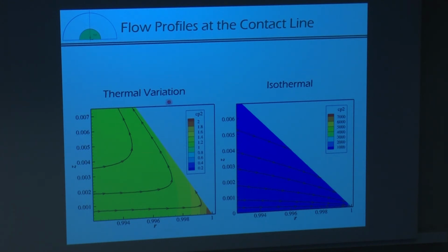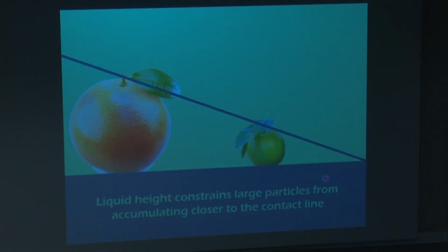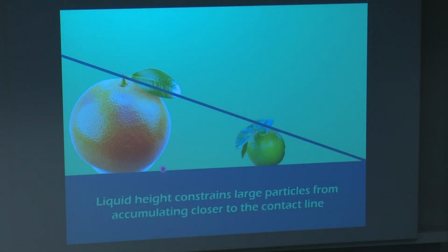So with thermal variation, you don't get very rapid deposition of the big particles at the contact line, whereas when you have isothermal conditions where the flow can go directly to the contact line, you can have a very high concentration of particles at the contact line early on. So you have to include the thermal variation in the model. This whole thing about the particles not being able to reach the contact line is due to the fact that the liquid height constrains the large particles from accumulating closer to the contact line. So the small particles can get closer to the contact line.